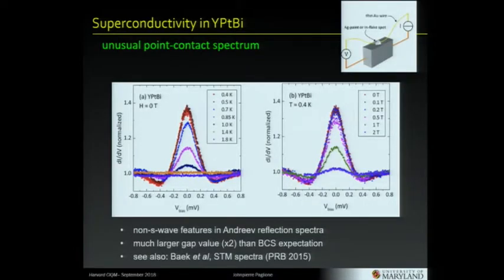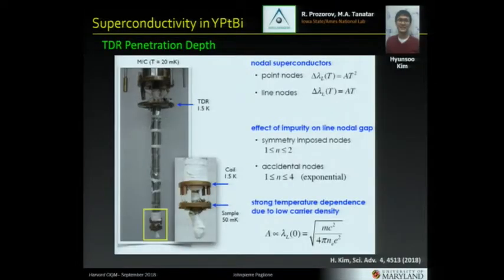So the first experiment we actually did was point contact spectroscopy, which shows a very unusual shape to the spectra. I won't go into details, but basically this is analogous to some kind of tunneling experiment, but it's not exactly tunneling. And this is a sign of some very strange Andreev reflection process that's not typical of an S-wave superconductor. So that was the first indication of something weird, and we, of course, followed up with more experiments. The most important being the penetration depth experiment shown here, done by Hyun-Soo Kim when he was a student with Prozorov, and then he came to work with me after.